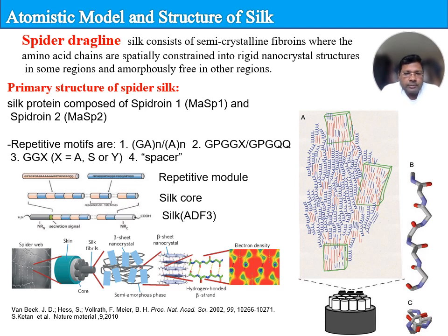The schematic of the hierarchical spider silk structure, ranging from nano to macro, displays key structural features of the silk that include electron density at the angstrom scale, hydrogen bonding strengths, beta-sheet nanocrystals, a heterogeneous nanocomposite of stiff nanocrystals embedded in a softer semi-amorphous phase, and silk fibrils which assemble into macroscopic silk fibers.